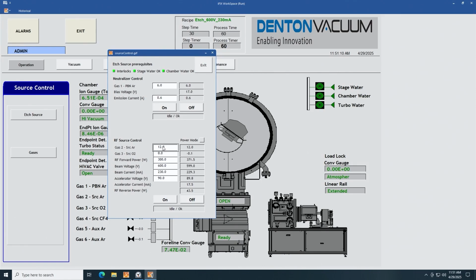Okay, so now that the source is lit, I'm going to turn down the gases to the actual process condition. That's 600 milliamps and 6 SCCM argon through the neutralizer. I'm going to turn this down to 12 SCCM through the source. I gave it a little extra gas just because it helps it light, but now that it's lit, I'll turn it down. Actually, the SIMS likes the pressure to be as low as possible. You also see the reflected power drop considerably. So the source and the SIMS both like the gas to be as low as you can make it while the source is still stable.